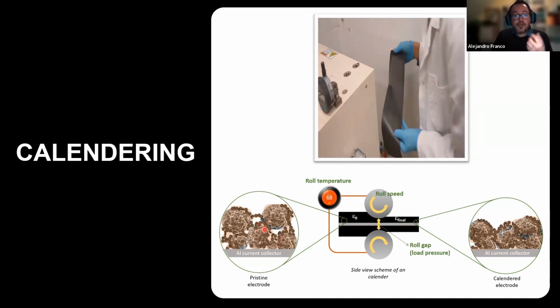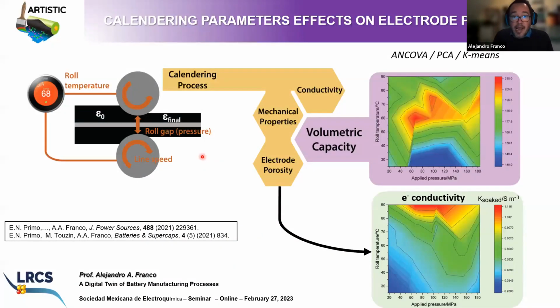pores inside the electrodes being fully collapsed, because if these pores become fully collapsed, then the liquid electrolyte that you need in order to exchange lithium ions properly between the two electrodes is not going to wet the porosity properly. This is a very complex process step because in a calendaring machine, you can control basically three types